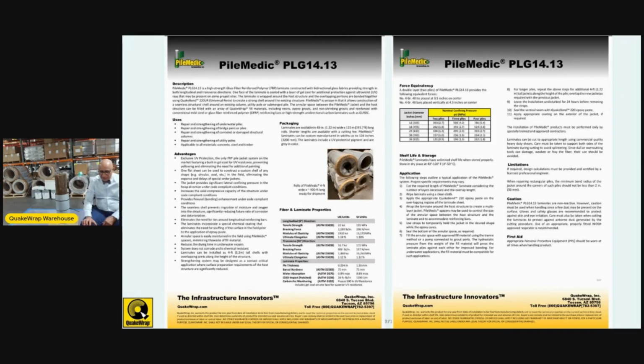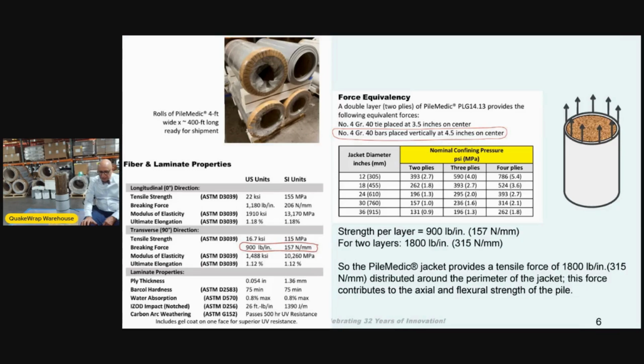On the next slide, I'm zooming in on a couple of these tables on our product data sheet. If you look here, you see that, for example, in the transverse direction, a layer of this PileMedic has a breaking force of 910 pounds per inch. And because we typically wrap these in 2 layers, when you add them together, the 2 layers give you around 1,800 or 1,820 pounds per inch in the vertical direction.